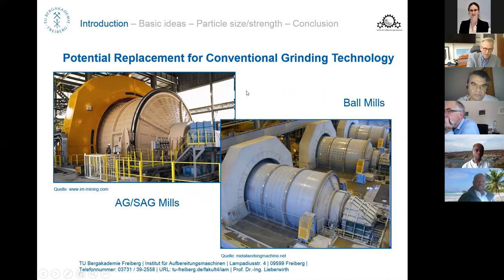In some cases, as for instance in El Salvador in Chile, you just have this one mill in the whole operation. So that mill does the whole processing from the rock size of 300, 400 millimeters to the flotation size, with recirculation of the material, etc. Is it efficient? Certainly not. But on the overall operation, there could be some arguments in favor of such a solution. So the typical solution nowadays is a combination of SAG mills and ball mills.